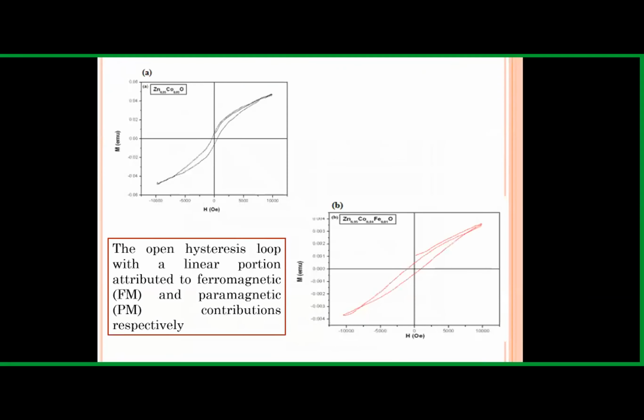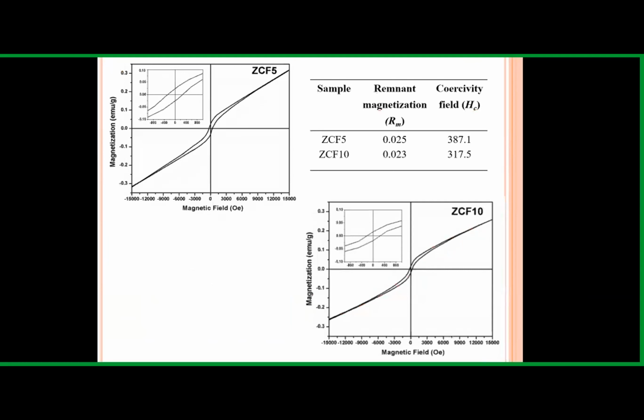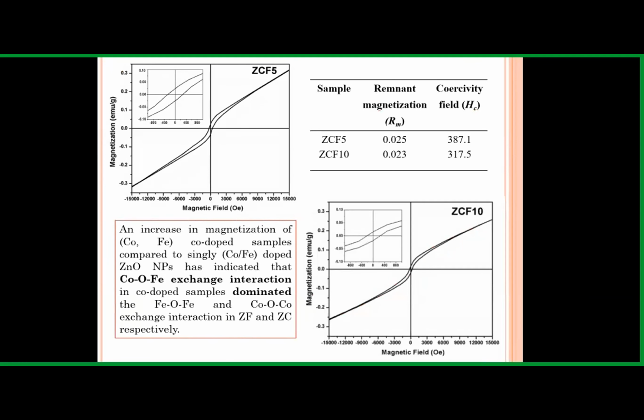As we can see, a good hysteresis loop was obtained with a linear portion; the open hysteresis loop is attributed to ferromagnetic behavior, and the linear portion to the paramagnetic nature in the cobalt doped sample. These are some of the studies we have done, and we can see an increase in magnetization in the co-doped samples. In the cobalt iron doped zinc oxide nanoparticles, the results indicated that cobalt-oxygen-iron exchange interaction dominated in the co-doped sample, whereas iron-oxygen-iron and cobalt-oxygen-cobalt exchange interactions dominated in the iron doped as well as the cobalt doped samples.